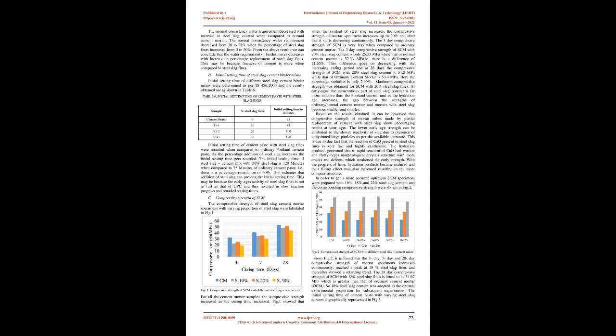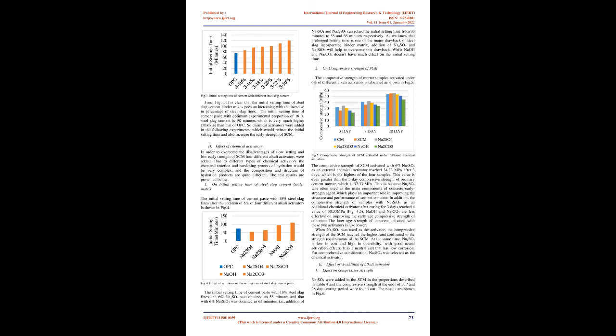Fig. 1 showed that when the content of steel slag increases, the compressive strength of mortar specimens increases up to 20% and after that it starts decreasing continuously. The 3-day compressive strength of SCM is very less when compared to ordinary cement mortar. The 3-day compressive strength of SCM with 20% steel slag content is only 25.33 MPa while that of normal cement mortar is 32.33 MPa, i.e., there is a difference of